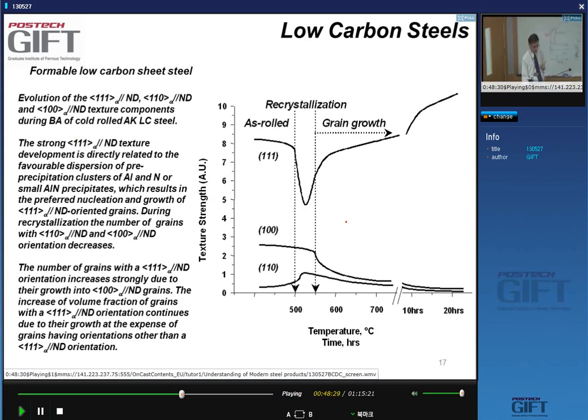Right. And people have studied this. The development of this texture is rather complex. And what appears to be important here is that the 1-1-1 texture is developed during the grain growth phase of the recrystallization.